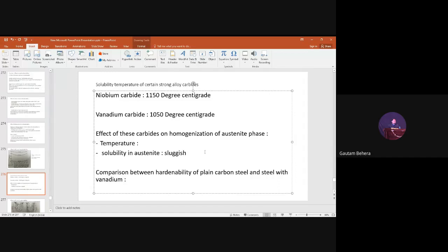Very slow. These carbides basically take much time to get soluble because of diffusion. The diffusivity, the D t, of these elements is very low.